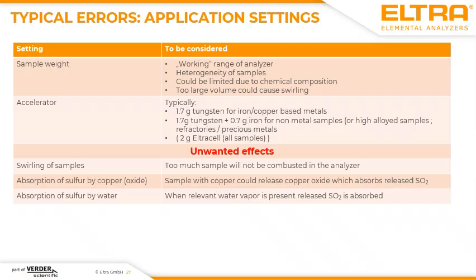The sample weight could be reduced due to the chemical base of the sample. When you have a sample, for example, which is based on a titanium powder, I would not recommend to apply more sample weight than 250 milligram, because the titanium in the sample can no longer be oxidized when it's present in too large a volume.